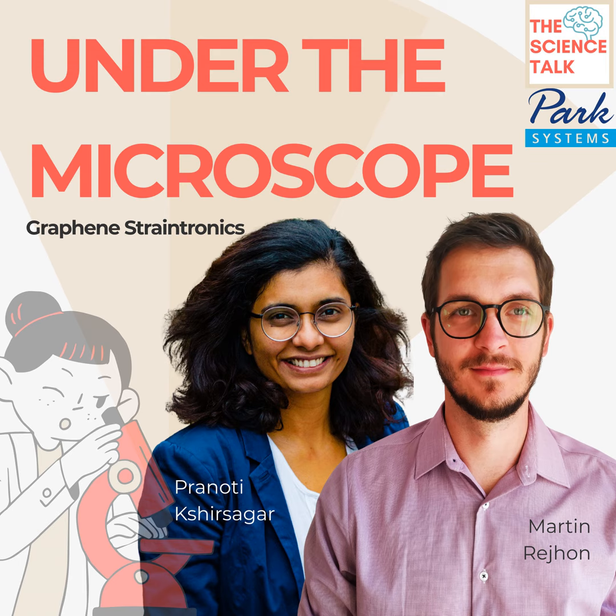What do you do? So mostly we do Raman and AFM. From Raman, you can see the quality of graphene, but the lateral resolution is poor because the laser spot is basically like 1 micron. So the best resolution I would say is around 100 nanometers or something like that. But to go down, then you have to use AFM. So we have a new AFM in my lab. We have the NX10 model from Park Systems. Amazing machine. Did you work with AFM during your studies?